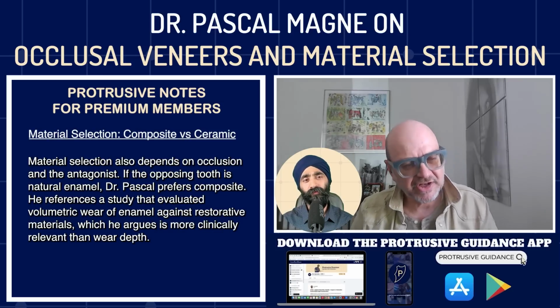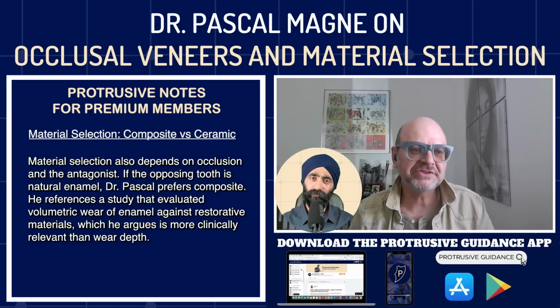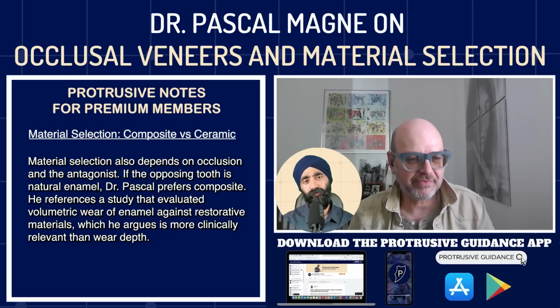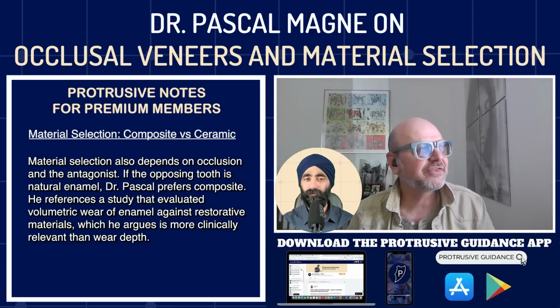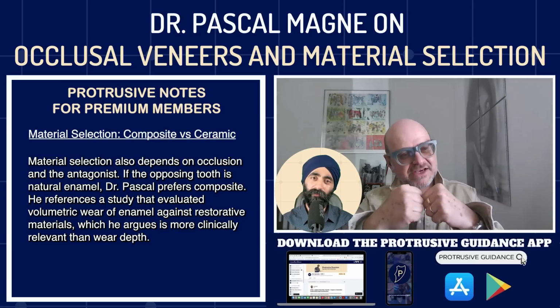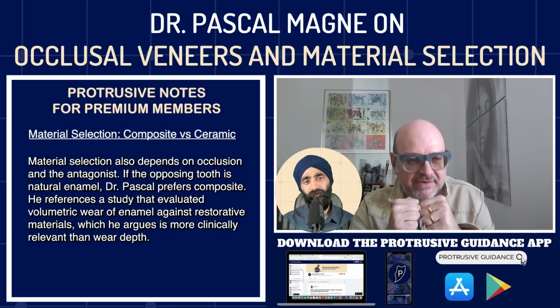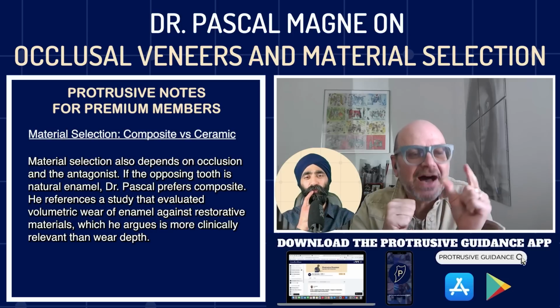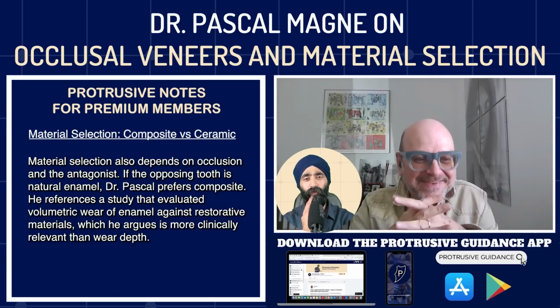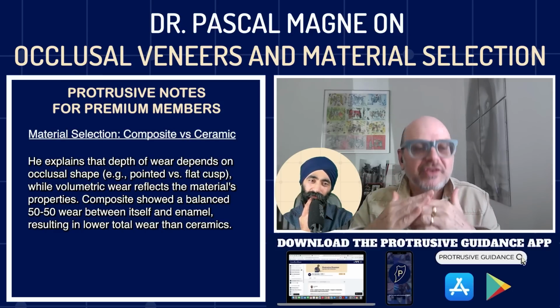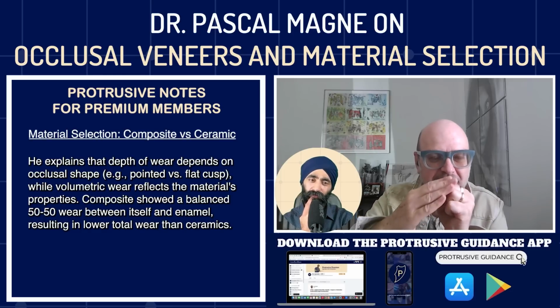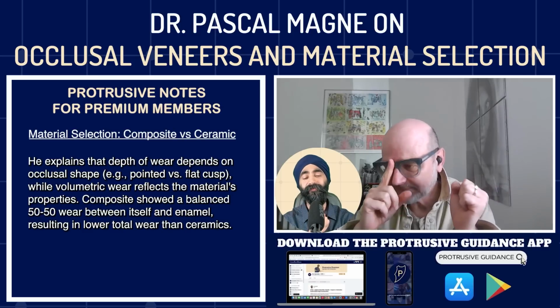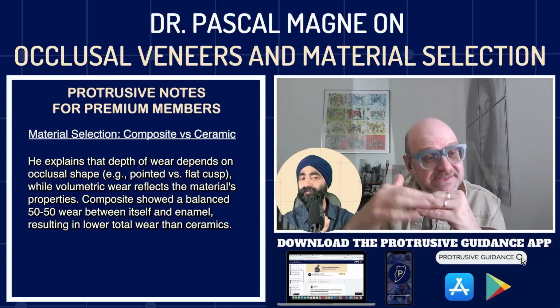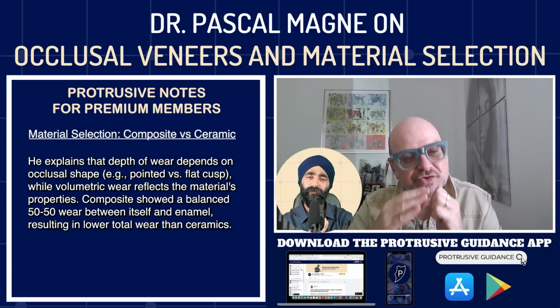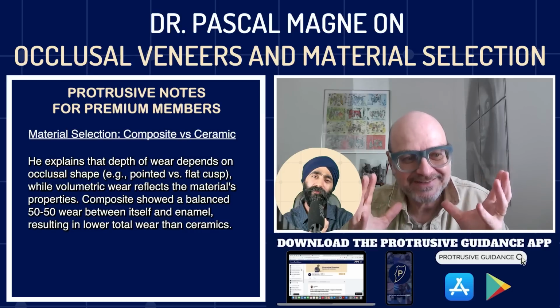The occlusal veneer definitely will be a little bit of a plus in terms of protection. And for the choice of the material, that's another important decision. You have to consider occlusion and antagonistic wear. So if the tooth facing that onlay is a natural tooth with enamel, I would always choose composite, because you have to look, there's a very good study about wear of antagonistic cusps. So you have to look at the wear as a volumetric wear. That's very important, because most studies measure wear as height of wear. And you have to understand, and I try to explain that in my book, depth of wear is an occlusal property. Because imagine when you have a very, very pointy cusp, you will lose a lot of height, but not necessarily a lot of volume. When you have a wide cusp, you might lose less height, but still a big volume. So the depth of wear is an occlusal property.